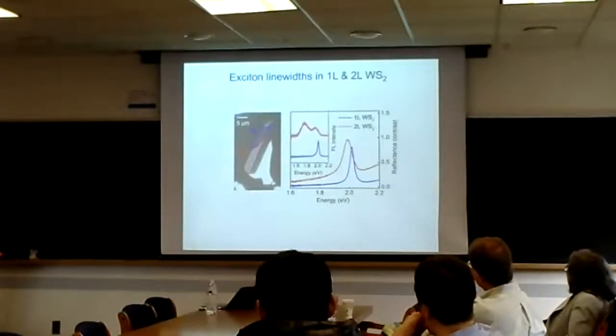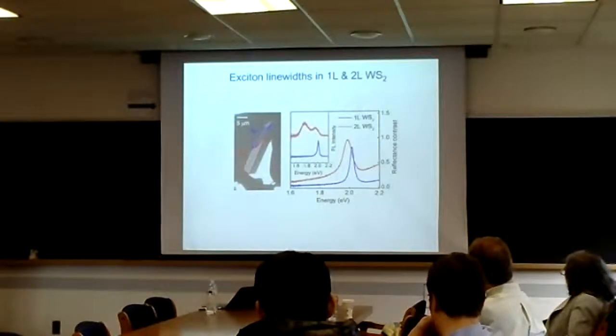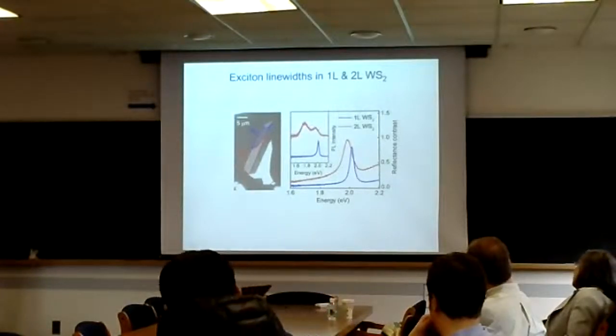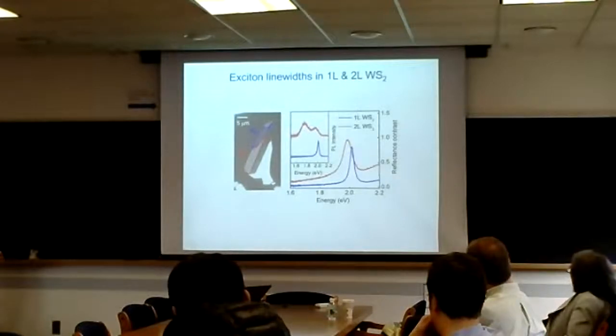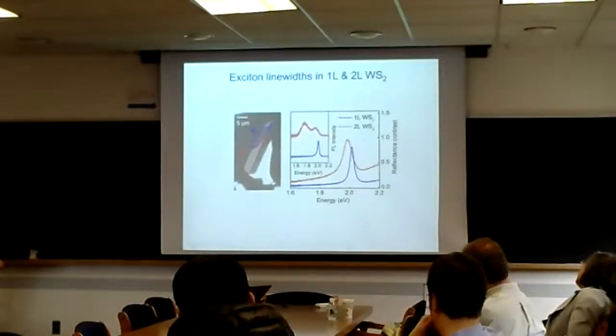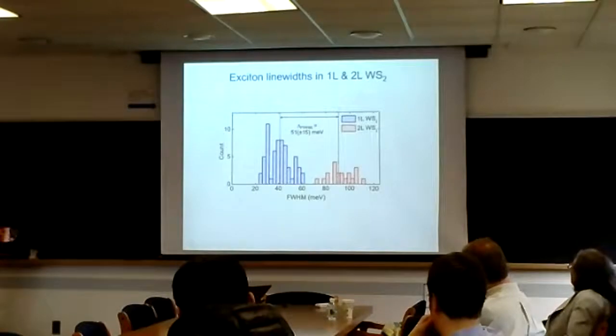So we have a system like this. You have a monolayer of material, you have a bilayer of material. This in blue is the monolayer, it's fairly sharp, and the bilayer, you can immediately see that it's broader. The monolayer is a direct gap because the absorption and the emission here are pretty much the same, but the bilayer is an indirect gap. So initially, the first thing when we saw the data was like, sure, it's going from a direct gap to an indirect gap. That's why you have more efficient phonon scattering and dephasing, because you have more density of states to go into. But we looked at statistics.